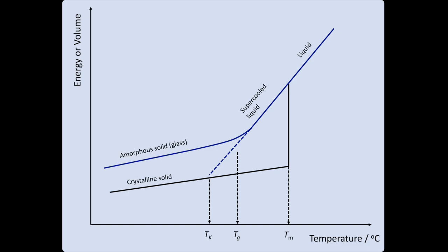Melting is called a thermodynamic transition because the only thing stopping a crystalline material from melting is energy. Once it has sufficient energy to overcome the bonds in the crystal lattice, it will melt instantly, with all bonds breaking at the same time. It doesn't matter how quickly a crystalline material is heated — we will always see melting occur at the same temperature. Glass formation, however, is a result of the rate of molecular movement reducing, and because it is a change in rate, glass formation is a kinetic process. This is very important: changes in rate require time, which is why the glass transition does not appear as a sharp discontinuity, and it means the temperature range over which we see glass formation will be affected by cooling rate.